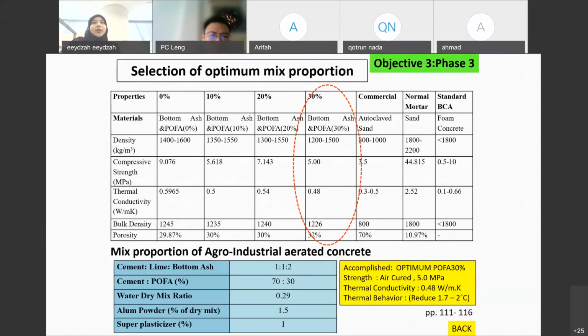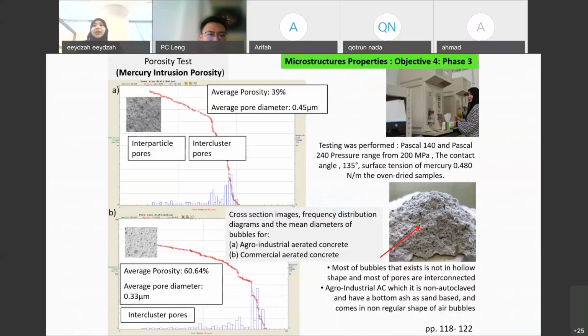Right. So again, this is looking into the density. It ranges between 1200 and 1500. The compressive strength is 5 megapascal. I'm looking into the lower thermal conductivity, which is 0.48, as compared to commercial at 0.3 to 0.5. But again, commercial uses high steam, so we try to ignore the high steam. The porosity created is about 32% as compared to commercial at about 70. So it's still acceptable in our condition for the material. And this is what my material is.